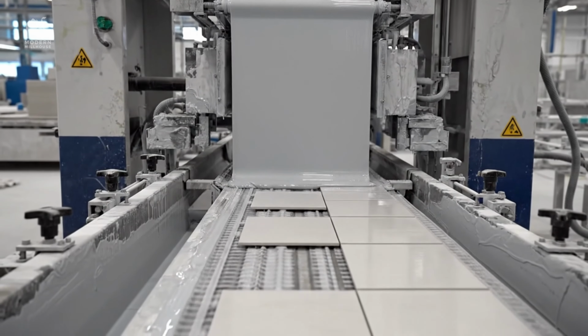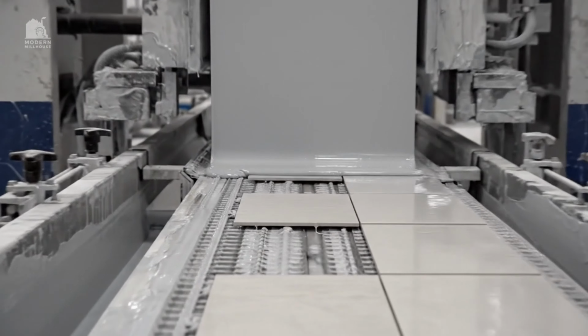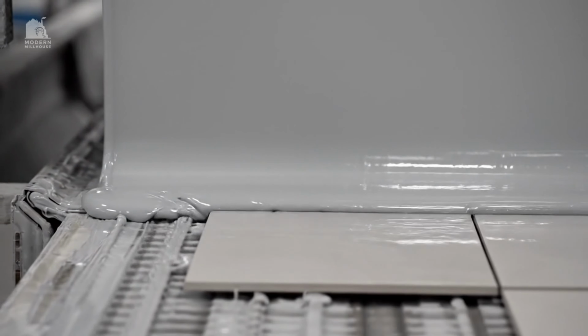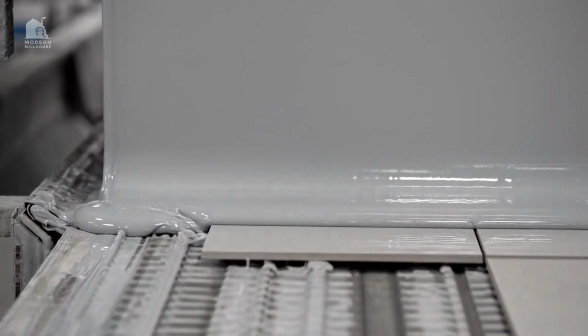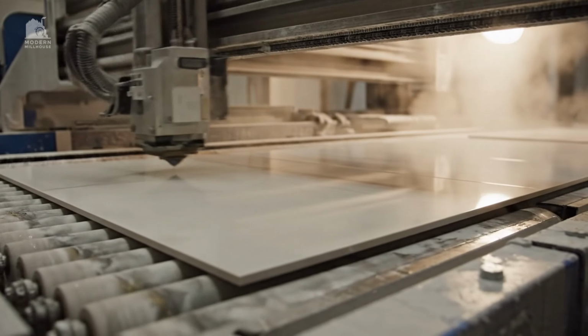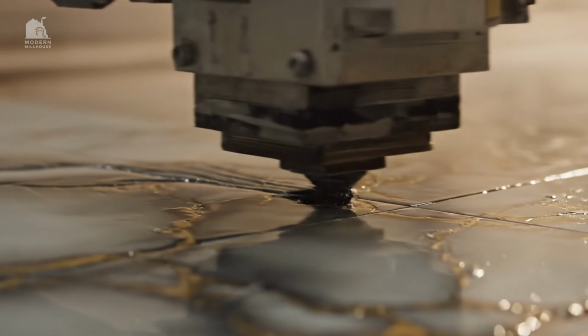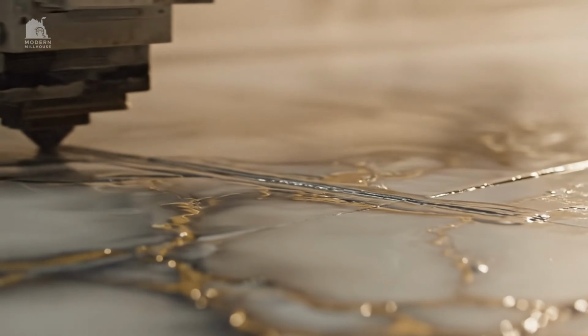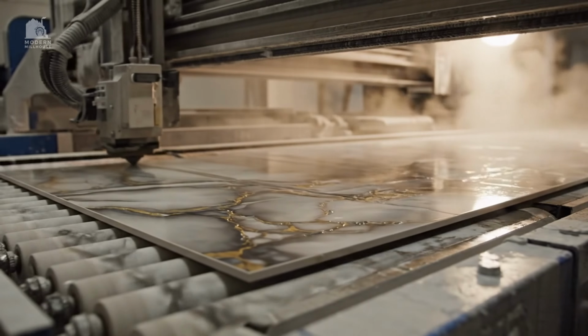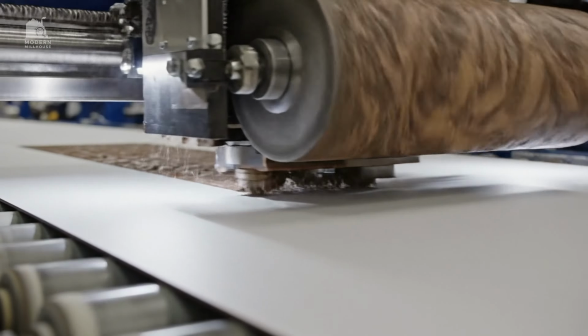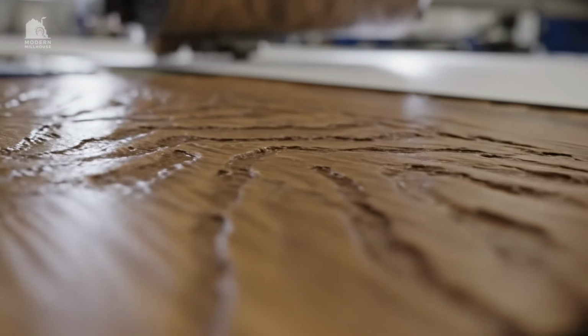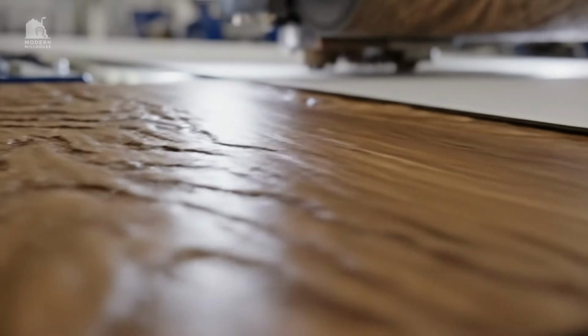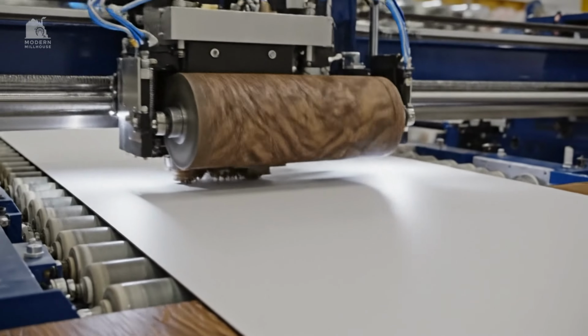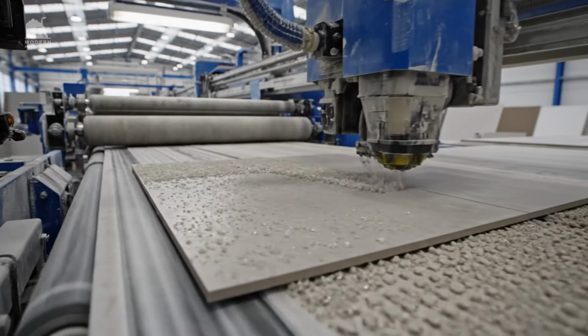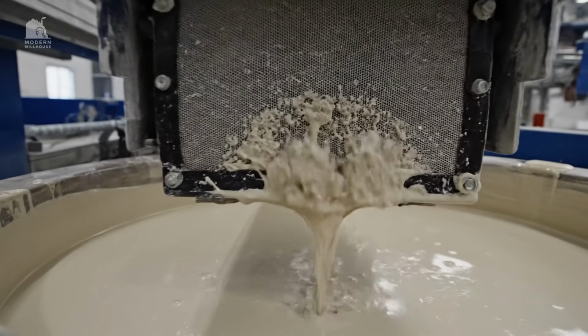Thickness is controlled in tenths of a millimeter because many glaze defects are thickness defects. Too thin and the surface looks dry and uneven. Too thick and glaze can run in the kiln, pool at edges, or crawl away from contaminated spots. Factories monitor glaze density and solids content, topping up water and additives to keep the mix stable. They filter glazes to remove clumps that could leave bumps or cause pinholes.